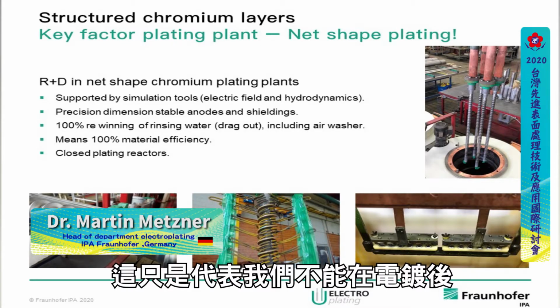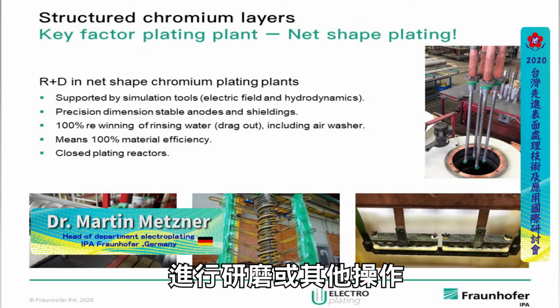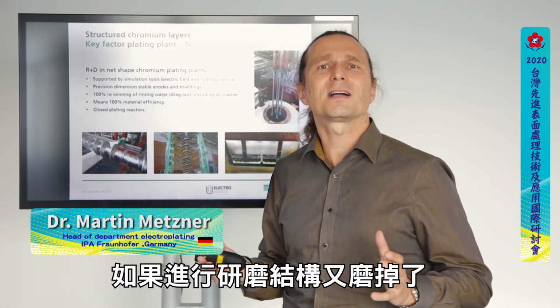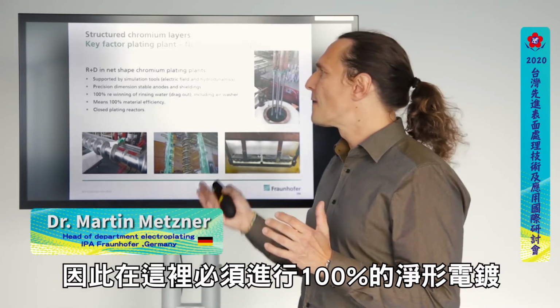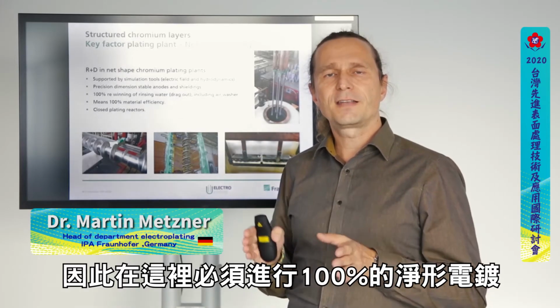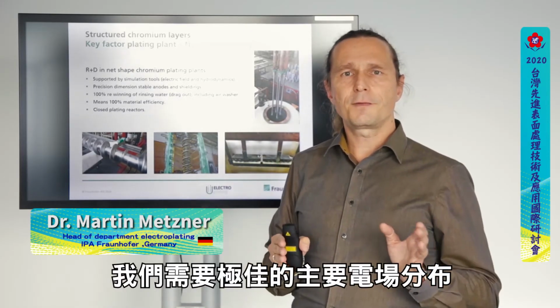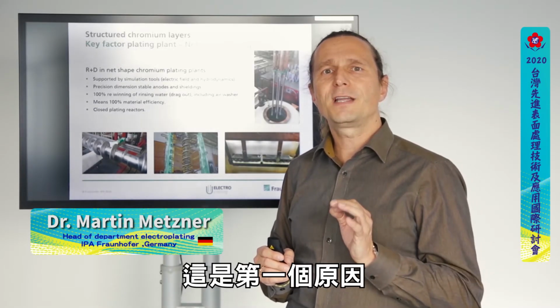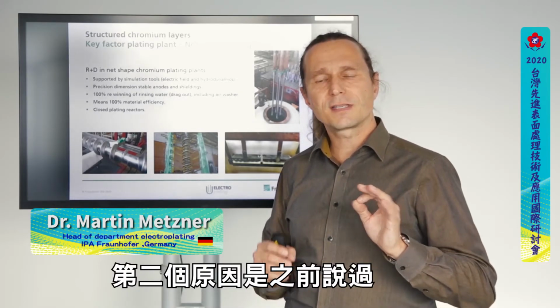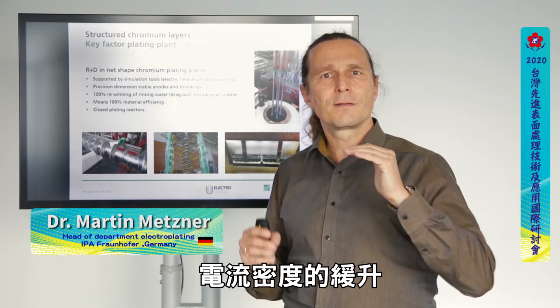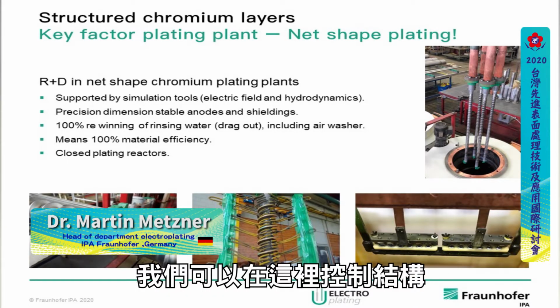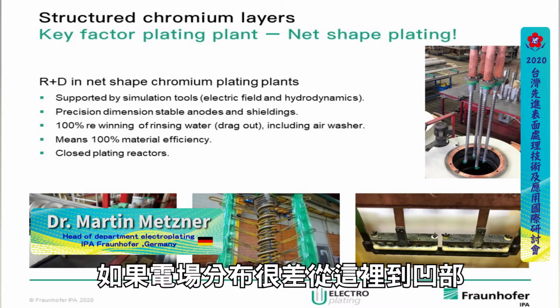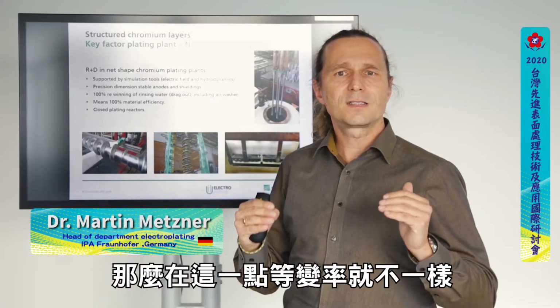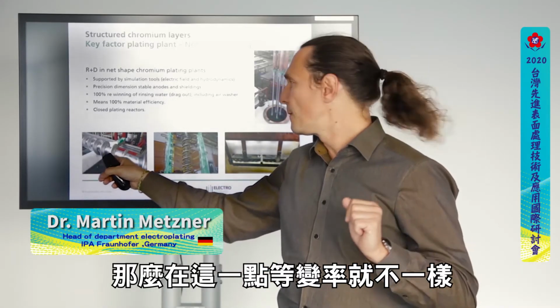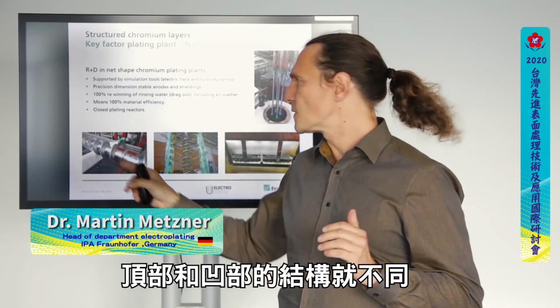This just means that we cannot do some grinding or anything afterwards, after the plating, because if we would do grinding, then we grind the structure away again, and this is what we do not want. And this means we have to go into a 100% net shape plating in here. This is the first reason why we need a very, very good primary electric field distribution in here. And the second reason is, I told you before, the ramp up of our current density. This is how we can play with the structure, we can control the structure in here. And of course, if we would have a bad electric field distribution on the part from here to the valley in here, a different electric field distribution, then this would mean that on this dot we would have another ramp than in here, and we would have different structures on the top and on the valley.